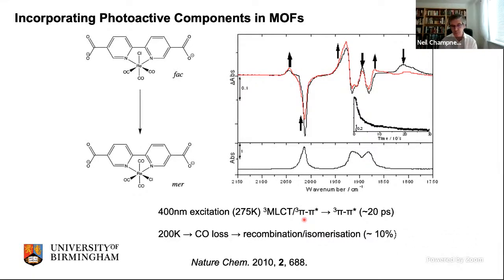Well, what is significant about this is that if you study these types of compounds in solution, the favored excited state is the metal to ligand charge transfer. So the MLCT state is what you see in solution. In the solid state or in the MOF, you see the pi star state. So you've actually inverted the energy levels of the excited state by putting this inside a framework structure. And that gives us hope that we can actually manipulate photochemical processes within frameworks like this.